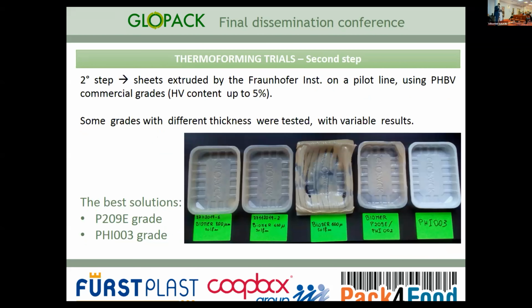The second step was to start using the material that was extruded by Fraunhofer using some commercial PHBV grades. Different grades were tested, as was explained in the previous presentation, also with different thickness, because thickness is quite important to have good results on the tray. As you can see in the picture, results were very different. We had very variable results. In some cases, we can get quite well-formed trays, like in the case of PHI003 and also in the case of the P209E grade.